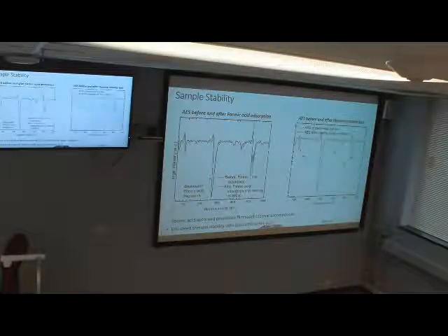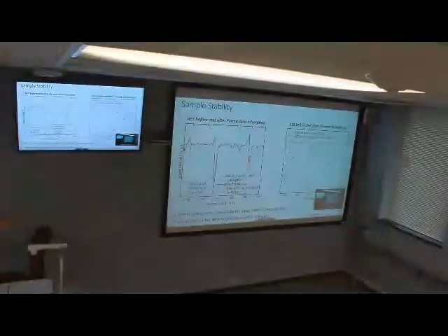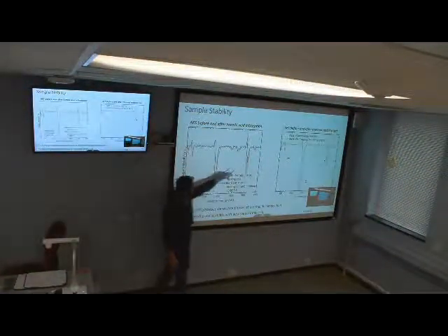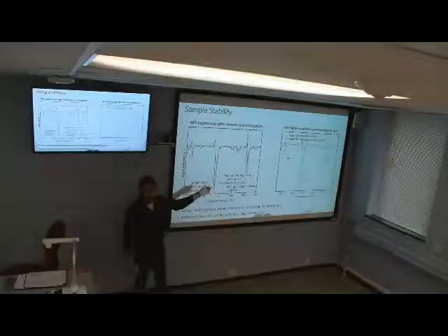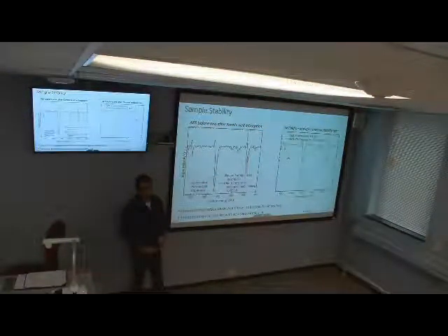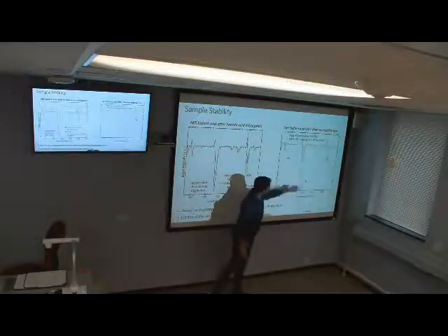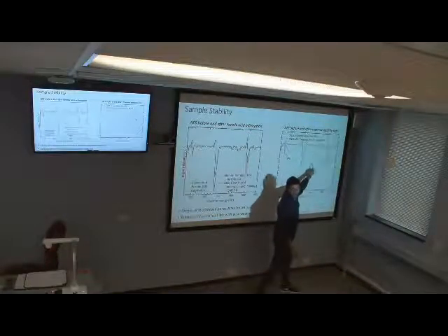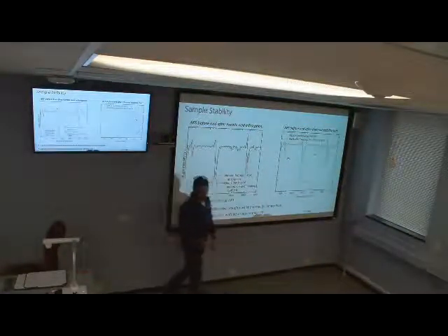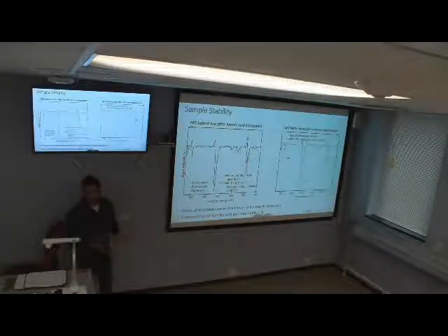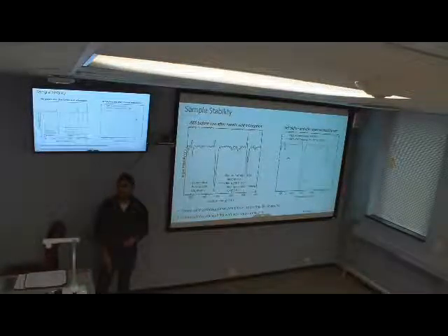With that thermal ramp, the structure changed a little bit. The intensities are quite different, but still we have the perovskite structure here. But without the formic acid layer, the structure is completely decomposed, completely destroyed. So we don't have the perovskite anymore. So with the same temperature, we have some improved stability. That was the main thing, I guess.